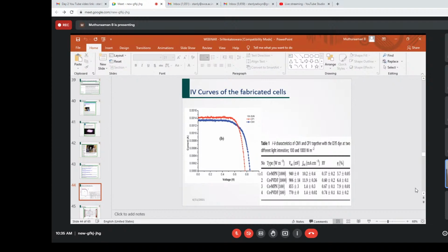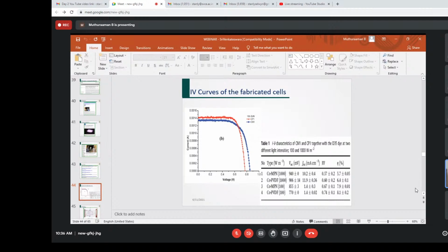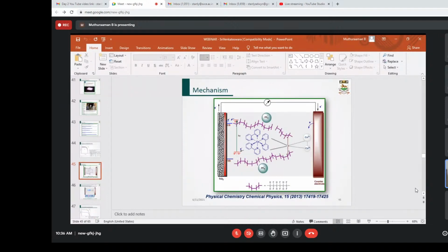You can see this one has a very good fill factor, and the curve shows the performance of the solar cell. This curve is called the current-voltage curve, or IV curve. Here you can see the cobalt with the polymer got 8.1% efficiency in indoor light. It's highly stable. This electrolyte we have given to a company, G24i, which makes flexible solar cells. So this forms the mechanism. A kind of polarization takes place with the redox materials, and charge exchange takes place. This is how it works.